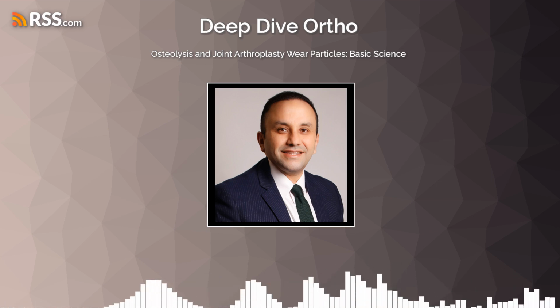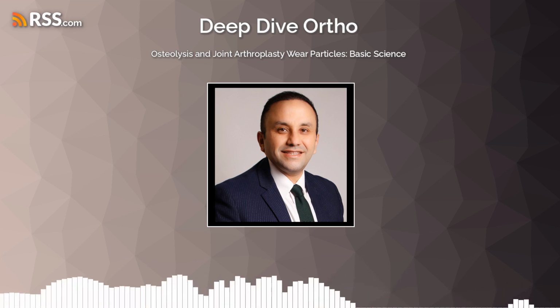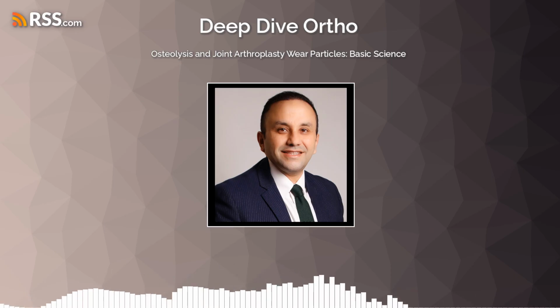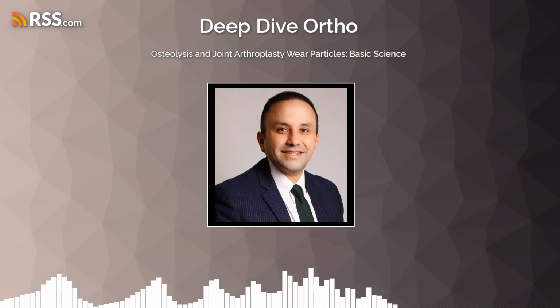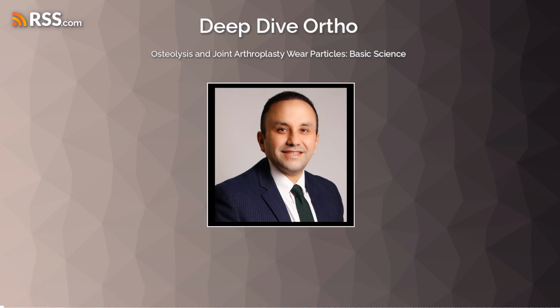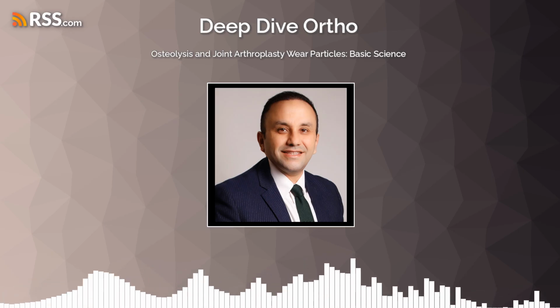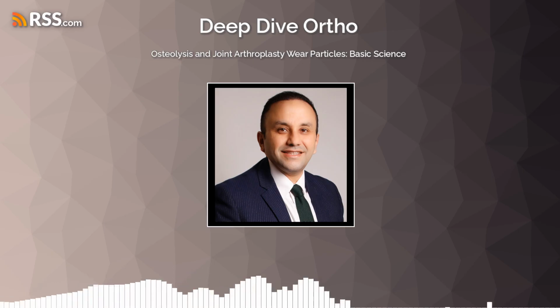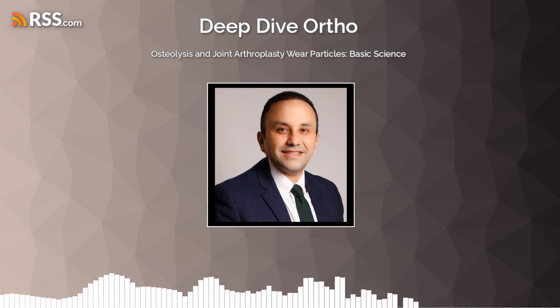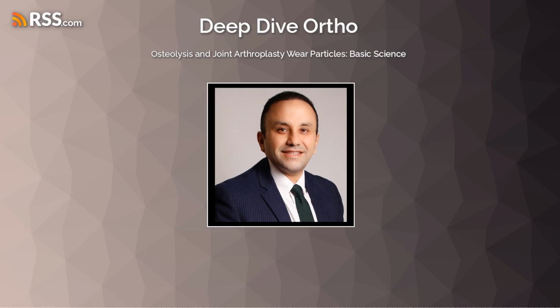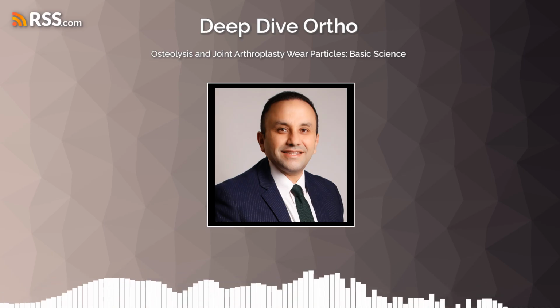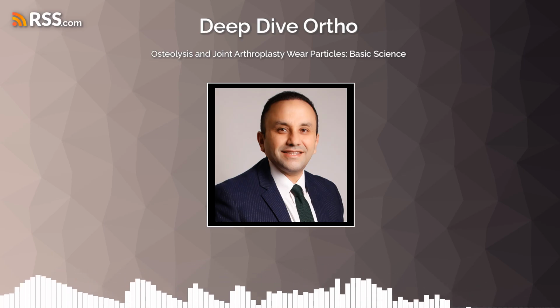Right. Let's start with polyethylene, maybe. It's been around a long time. Yes, polyethylene, specifically ultra-high molecular weight polyethylene, or UHMWPE, has been a cornerstone material in arthroplasty for decades. Conventional, non-cross-linked UHMWPE historically had wear rates typically between 0.1 and 0.2 millimeters per year. While widely used, its wear particles are a well-known potent cause of osteolysis.